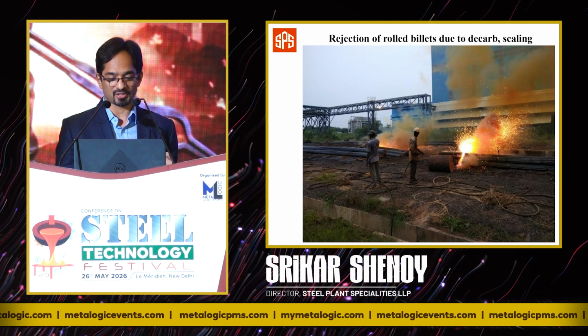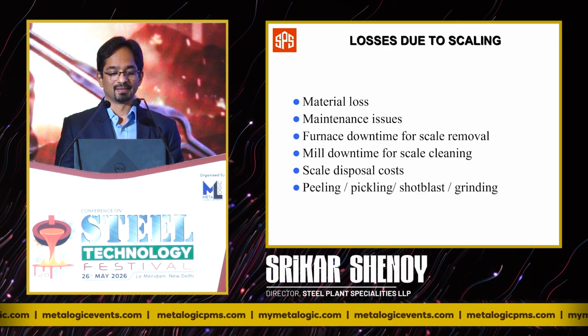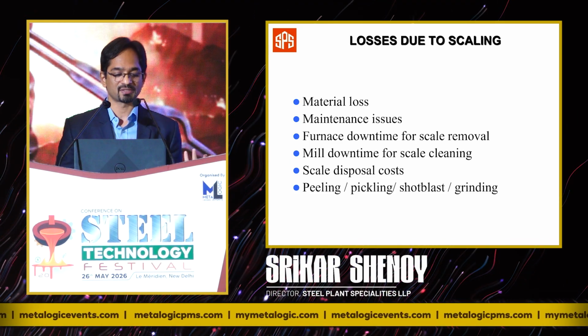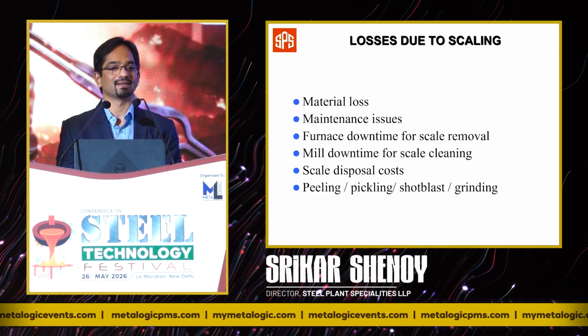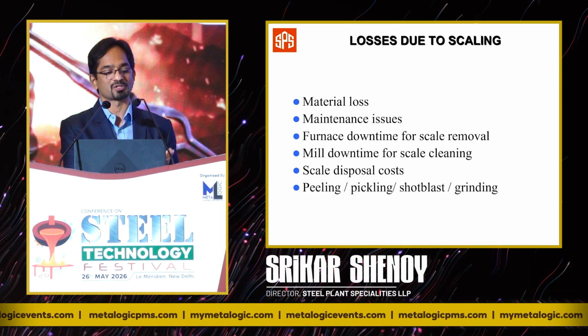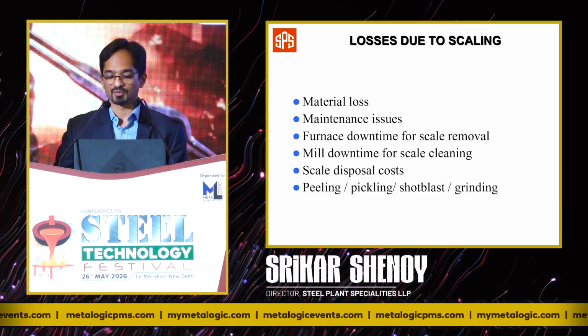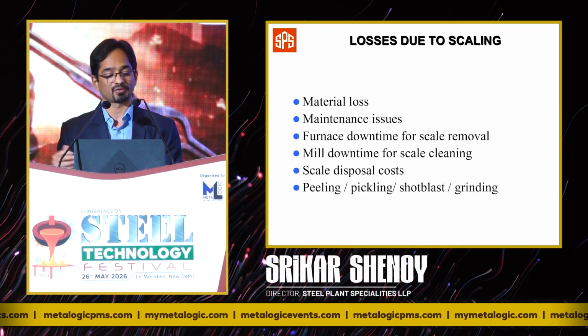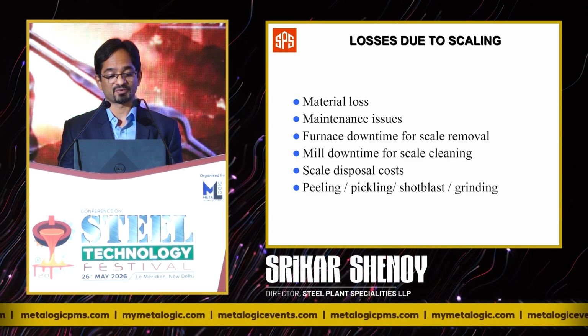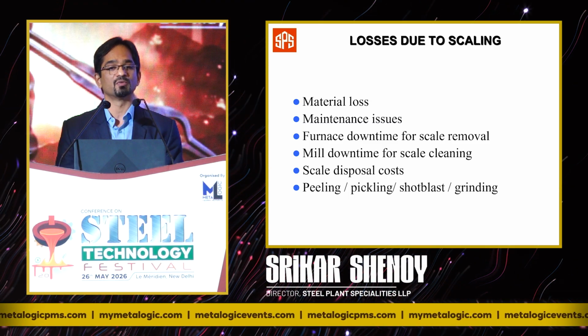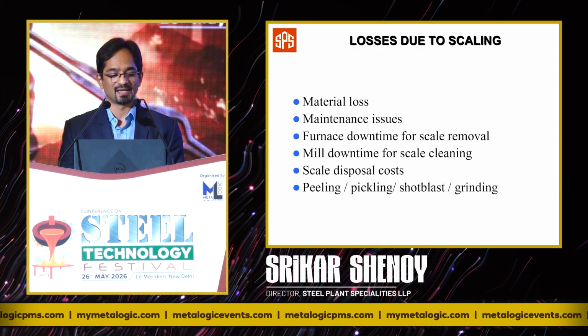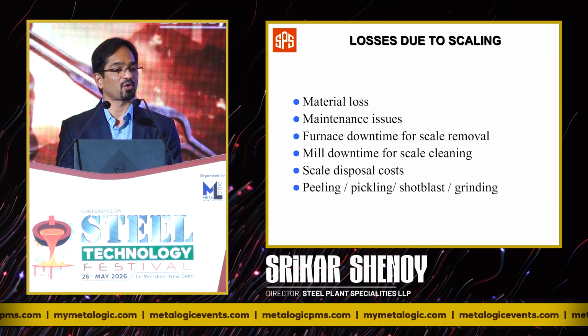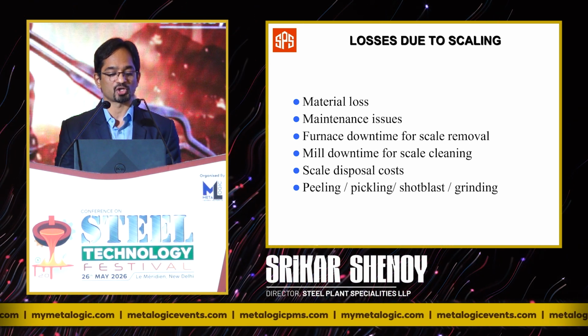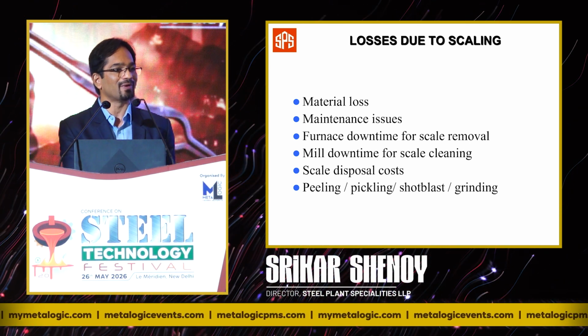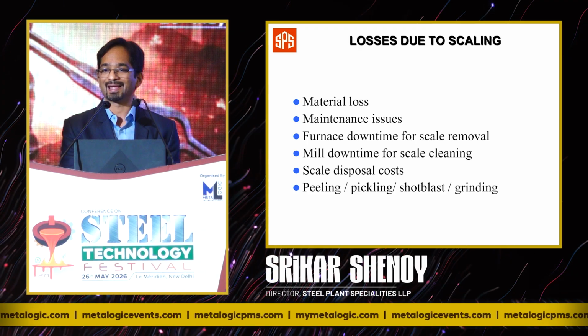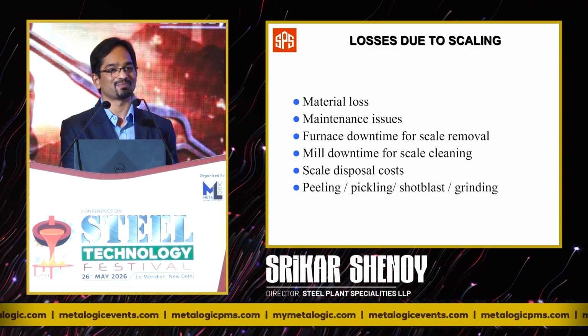Apart from direct loss like rejections, due to scaling, you have material loss, maintenance issues. The scale gets adhered to the rolls, which causes quality issues. It damages the hearth of the furnace. A lot of times, furnace downtime is taken just to remove scale from the rolling mills and the furnaces at all. Downstream processes like peeling, pickling, shot blasting, these processes do not add value to the product, but they add costs, they delay your dispatches.